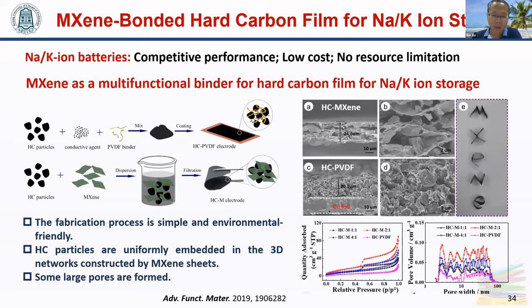And from SEM, we can see the hard carbons are uniformly embedded in the 3D networks constructed by MXene nanosheets, and some large pores are formed between the MXene nanosheets and the hard carbon particles. We can see that the film has very good flexibility. It can be folded into the word MXene.